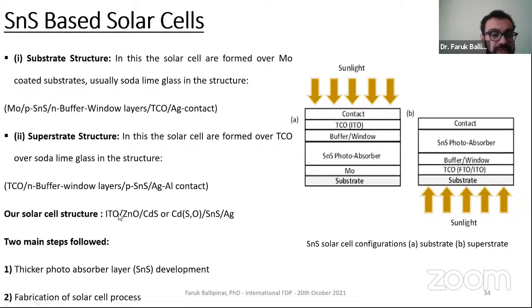Our solar cell structure is ITO, indium tin oxide substrate, zinc oxide, cadmium sulfide, and cadmium oxysulfide as the n-type, tin sulfide as the p-type, and silver top contact. So from the first part, we developed a thin photoabsorber layer, 100 nanometers. But this thickness is not enough to absorb photons and convert them to electricity. So basically, we need thicker tin sulfide development.